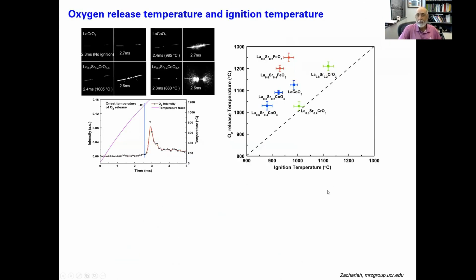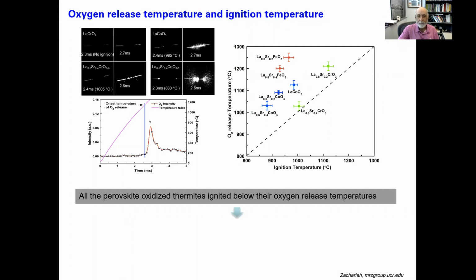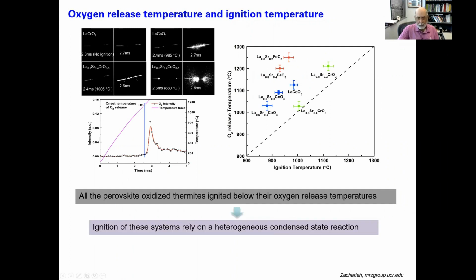So first I've got to see, how does the oxygen release compare to ignition temperature? And everything is above the diagonal. Now, what does that mean? It means that these systems must be igniting by condensed phase ignition, because it ignited before oxygen came out into the gas phase. So this is a condensed phase process that we're going to look at. So ignition of these systems relies on heterogeneous condensed state reaction. And therefore, that must be oxygen ion transport.